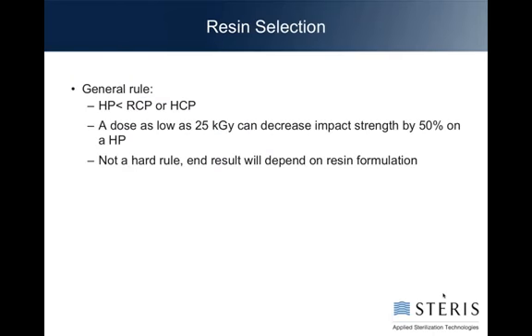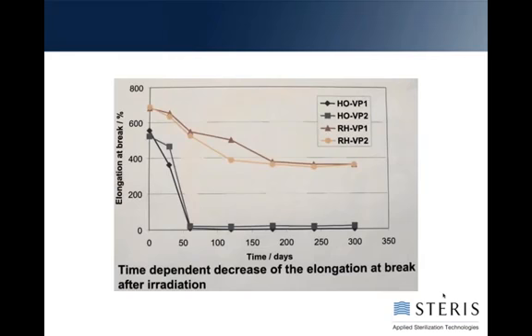Okay. So as a rule, homopolymers will be less stable than any form of a random copolymer. So when you first see homopolymer, it doesn't necessarily mean it's always bad, but it means you should probably ask some more questions. A dose as low as 25 kilogray can decrease the impact strength on a homopolymer of polypropylene by 50%. Not a hard and fast rule because that will depend on the specific resin, but you always want to ask questions once you start seeing the words homopolymer on a product.